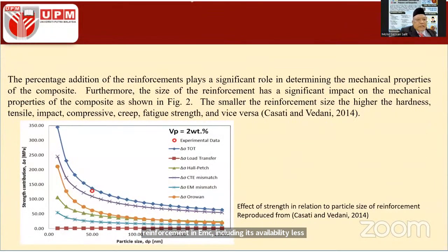The percentage addition of reinforcement plays a significant role in determining the mechanical properties of the composite. Furthermore, the size of the reinforcement has a significant impact on the mechanical properties of the composite, as shown in figure 2. The smaller the reinforcement size, the higher the hardness, tensile, impact, compressive, creep, and fatigue strength, and vice versa. So this figure shows the effect of strength in relation to the particle size of the reinforcement, and we can see that